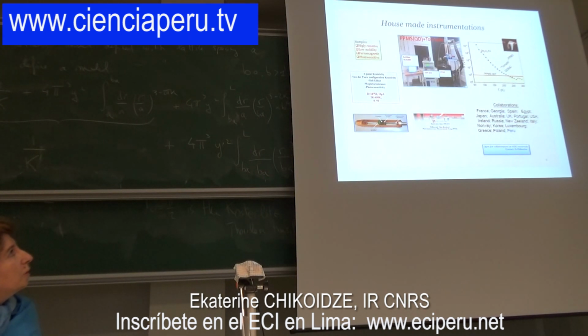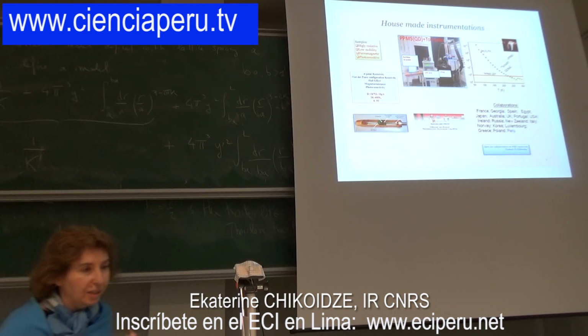And also on the same equipment a photo-optical probe was developed, so we can illuminate the material with any light, of course, and measure photoconductivity and even photoluminescence. So we also did a special application, which you can see on the Quantum Design website. Here are all the countries with which I have the pleasure to collaborate, and I hope that Peru will be added very soon to this list. And if you find it useful, we are very open to collaboration on wide bandgap materials, especially oxides.